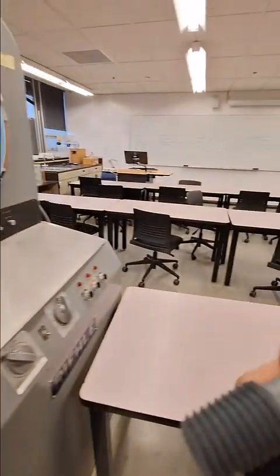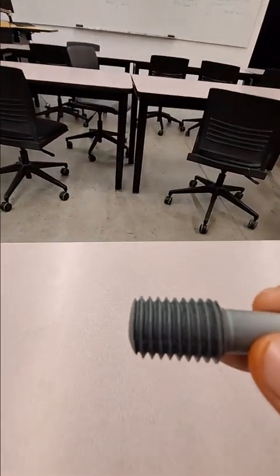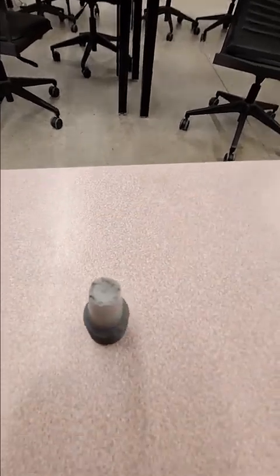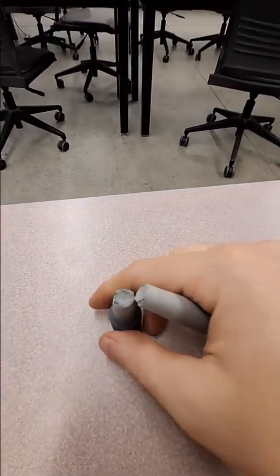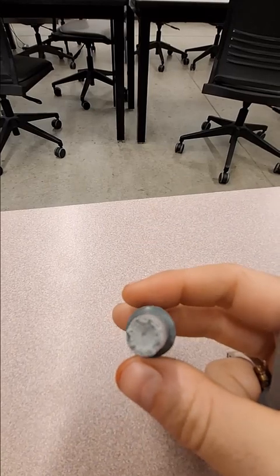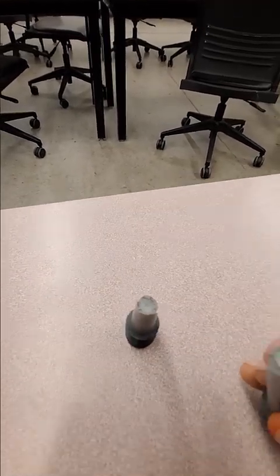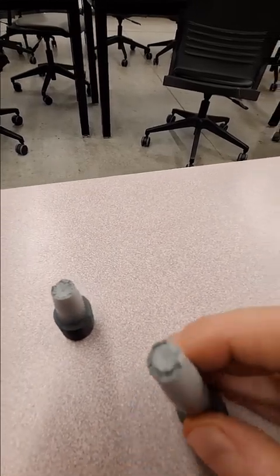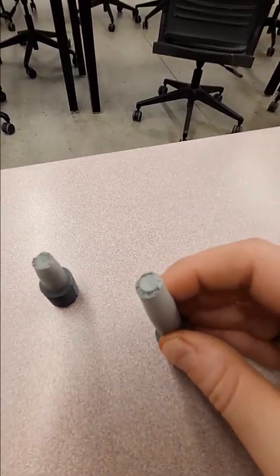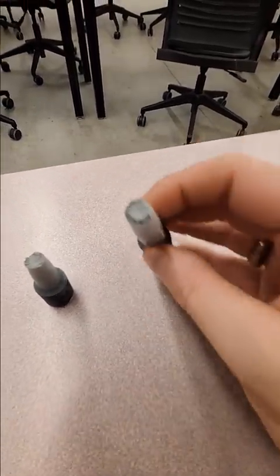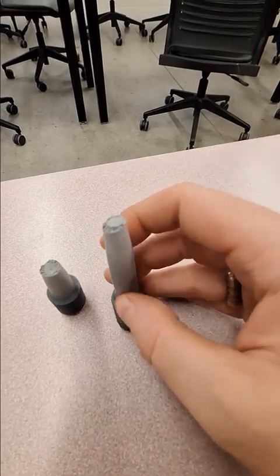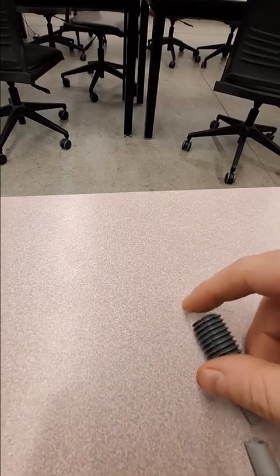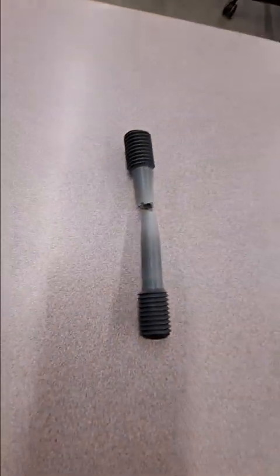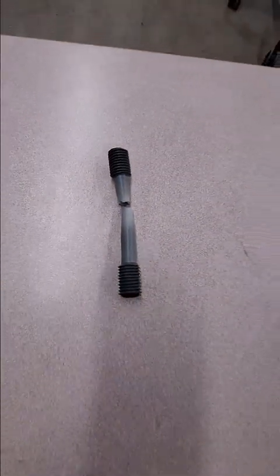Amazing. So you see in the grips, much darker because it's not elongating, but you can see that fracture tip right here. Gorgeous. Definitely ductile, but again, for polymers, that is a somewhat brittle fracture pattern. Now, you could take a whole course on fracture patterns and material structures, but you can see for a polymer, it did not extend significantly prior to fracture, at least for an amorphous polymer.